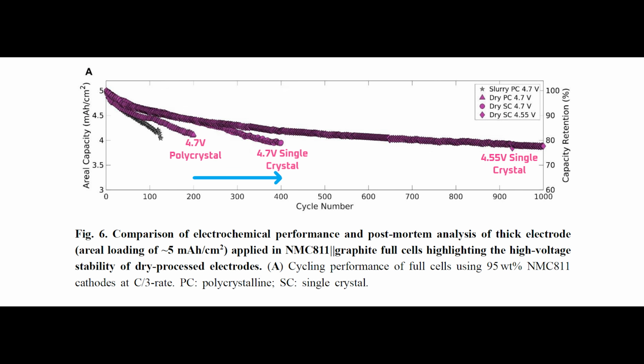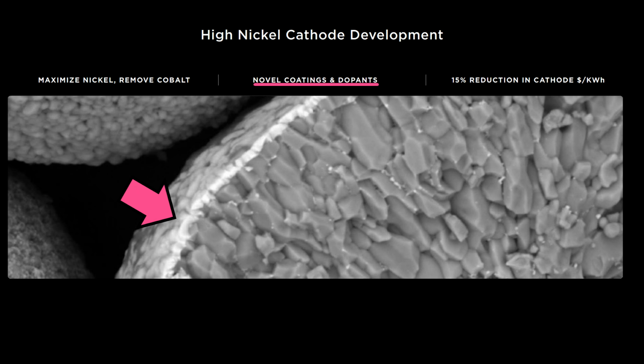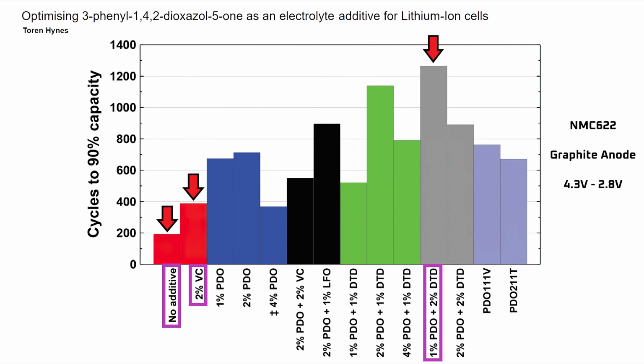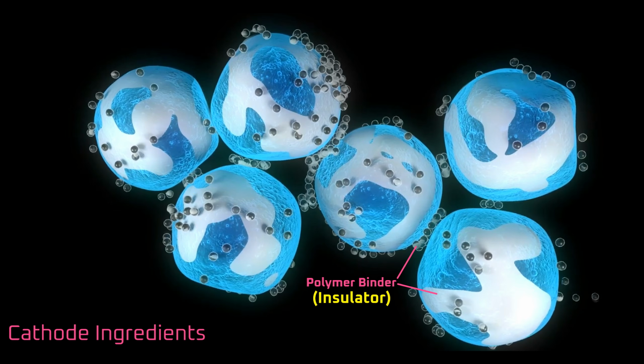With that said, although using single crystal cathode is an industrially acceptable shortcut to increasing cycle life, which is likely why the researchers chose it, there are other ways to increase cycle life that could be more cost-effective, such as better cathode designs and improved electrolytes. For example, Tesla could use some of the electrolyte additives developed by their research partner, Jeff Dahn. Those additives would essentially add no cost, but could easily match the 50 to 100% cycle life improvement provided by single crystal cathode material.